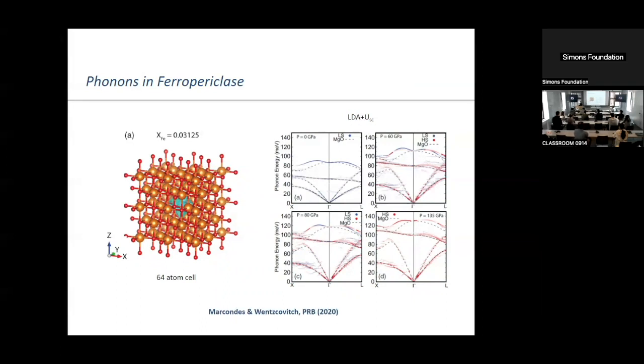And also conceptually, the answer may just be that it's dilute. Yes, exactly. But the theory you presented previously was essentially the generalization to this richer situation of the usual binary alloy thing. Now, I might imagine that somewhere in this I have a first order phase transition with phase separation. The binary alloy thing doesn't give me that. So where does phase separation come in around the first order transition? You may have that. If x equals 0.5, you may separate. You may have phase separation in two different ferropericlases with different composition. I see. But it's the small x's here. Yeah. Okay.